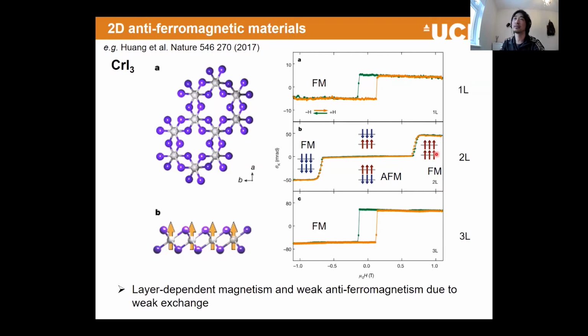So this is because the interlayer exchange coupling between these two layers is reasonably weak because of the van der Waals gap. So this gives you extra tunability due to this gap. And then you just put the third layer on top of it, then again we can recover back the ferromagnetic state. So that's really exciting. This is something we cannot do with conventional crystalline materials.